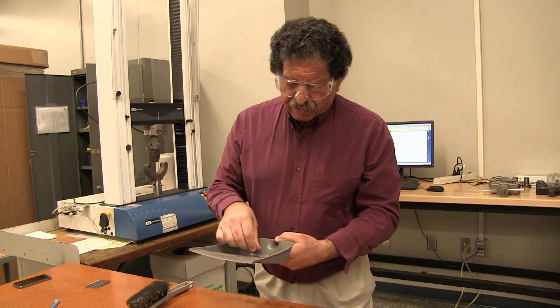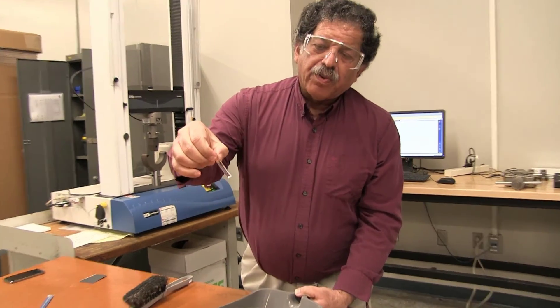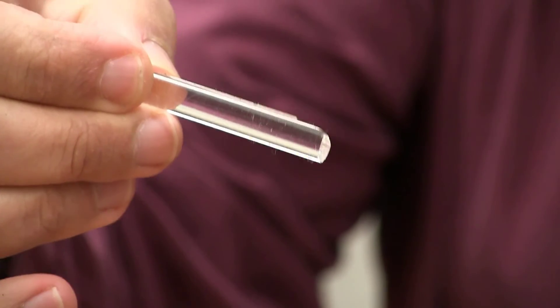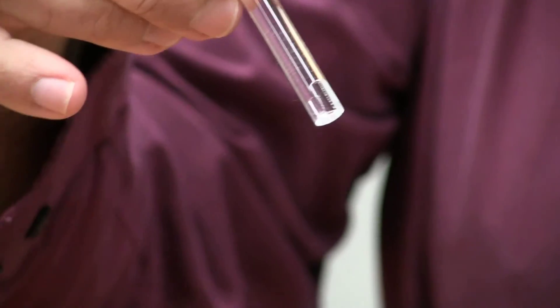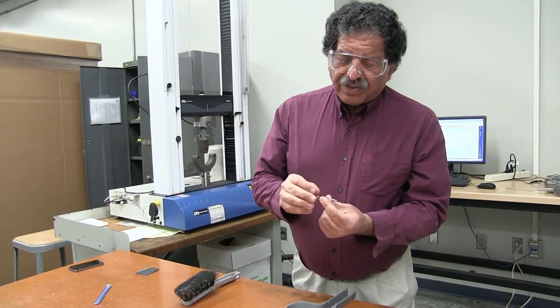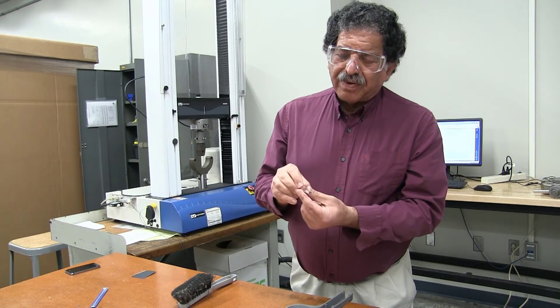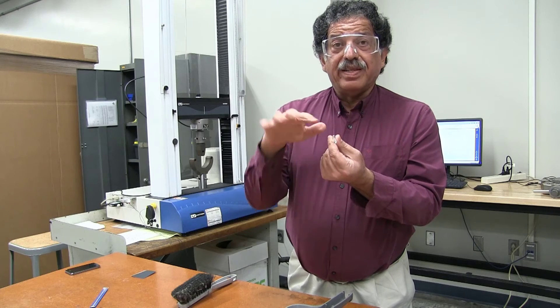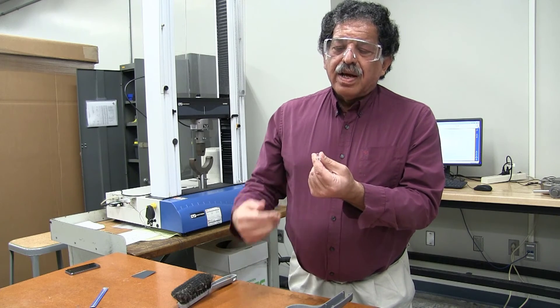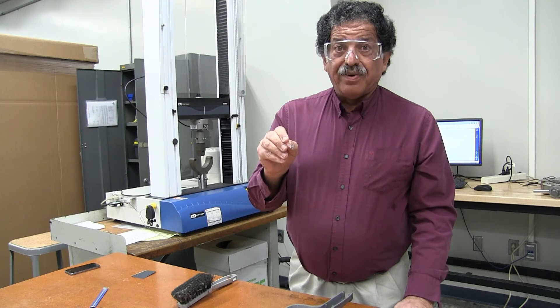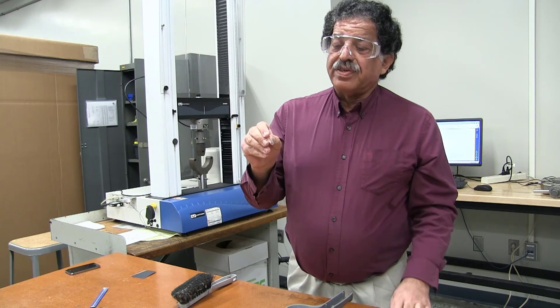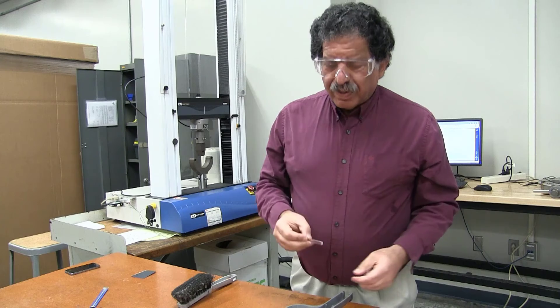Okay. And I'm not sure what you can see on this video, but there's some really cool surface features on the glass. If you were here and you could see it up close, you'd see these almost conchoidal fracture lines following the surface of the crack. Those are called Wallner lines. If you're interested in why those are generated, you can look that up. Wallner lines. And it has to do actually with the dynamic propagation of the crack. As the crack is propagating, stress waves are bouncing between the edge of the specimen and the crack surface. And the crack moves pretty close to the speed of sound in the specimen, and so you get these weird undulations of the crack surface. Really cool. Totally irrelevant to this lab, but really cool.